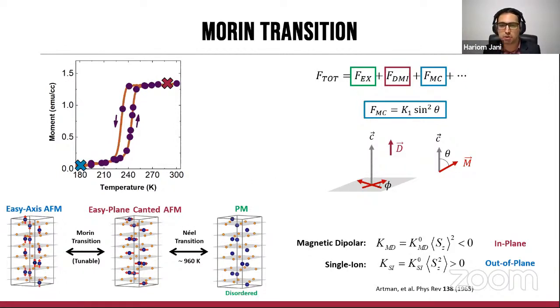Now, experimentally speaking, if we want to do Kibble-Zurek quenches, the ideal way would be to use the Néel transition, which is actually what was proposed, a second order phase transition. But this is experimentally very difficult to do. By the time you take realistic samples to those temperatures, you start to lose oxygen vacancies in vacuum environments. And therefore, it is much more preferable to use the other phase transition in the system, also called the Morin transition. To convince you that this is going to work, the key point to note is that the easy axis phase is in some sense topologically trivial because it only has the two ends of the unit sphere available to itself, whereas the easy plane phase is topologically rich, exhibiting effectively U(1)-like symmetry because the basal anisotropy is weak.